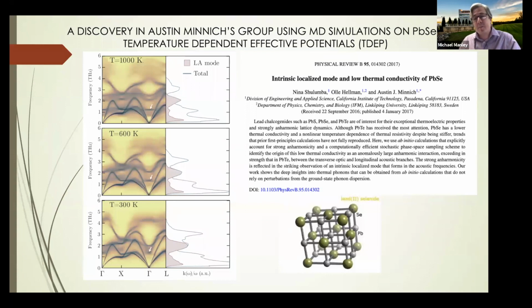And they did this on lead selenide, and then they looked at it at high temperatures, and you notice they got this localized thing here, this flat band. I say it's localized because it's not propagating. It has 0 group velocity, and the velocity, of course, is the slope. And they were looking at this and saying, what is this? And it affected the thermal conductivity.